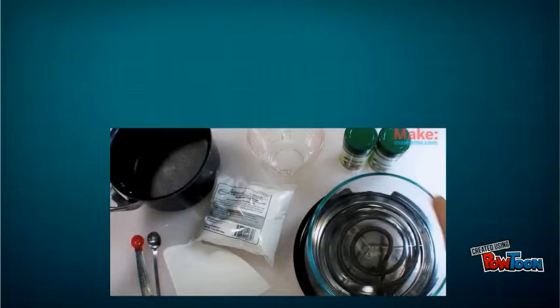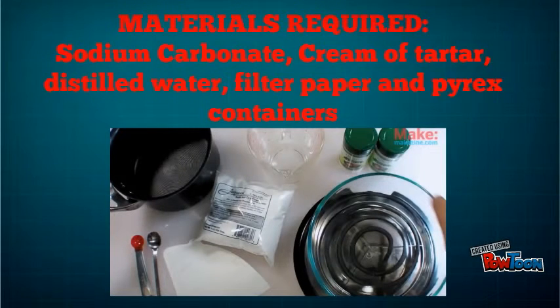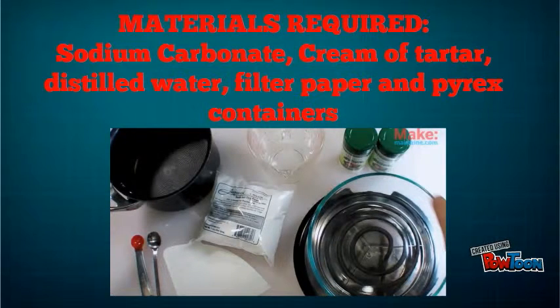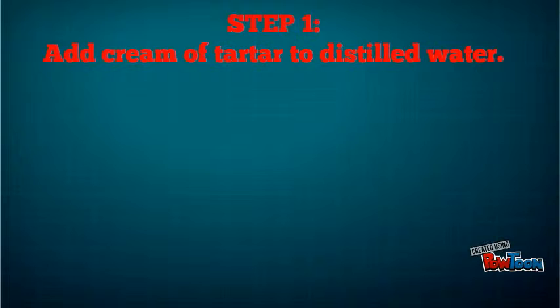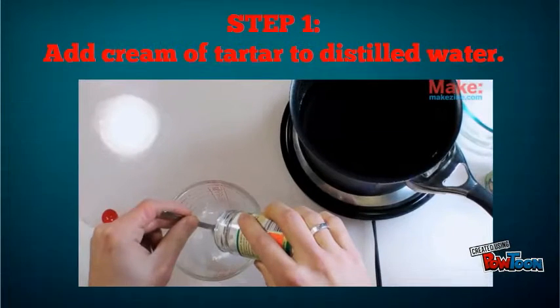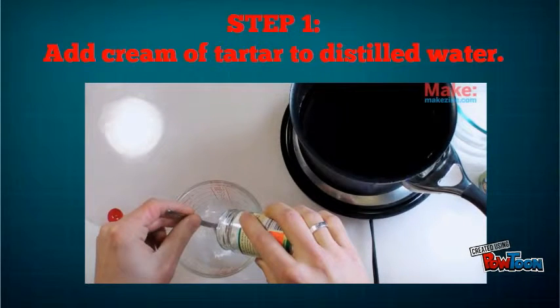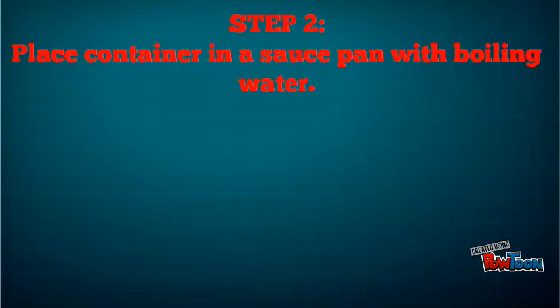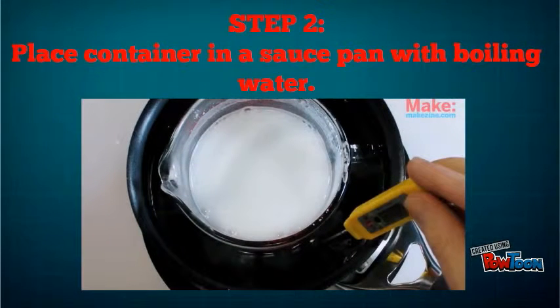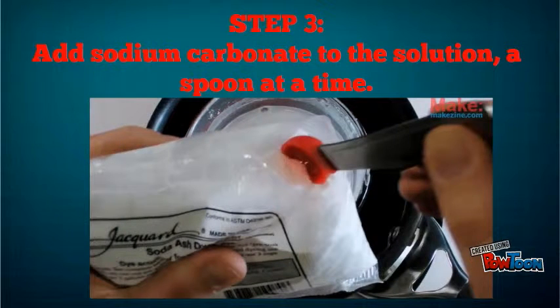Piezocrystals are very easy to make, just took us about 2 months. The ingredients required are soda ash or sodium carbonate, cream of tartar, distilled water, filter paper, and Pyrex containers. First, we add cream of tartar to distilled water in a Pyrex container. This container is then placed in a saucepan filled with boiling water and is heated. After that, soda ash is added to the mixture, 1 teaspoon at a time.